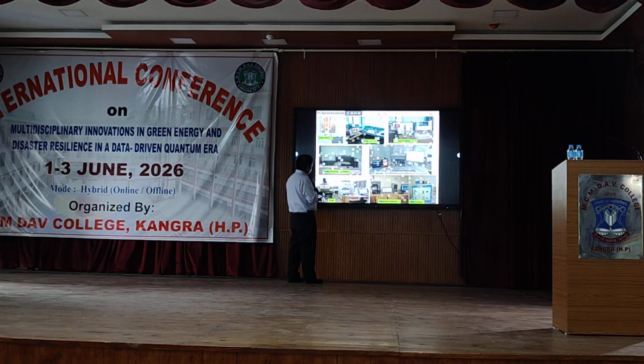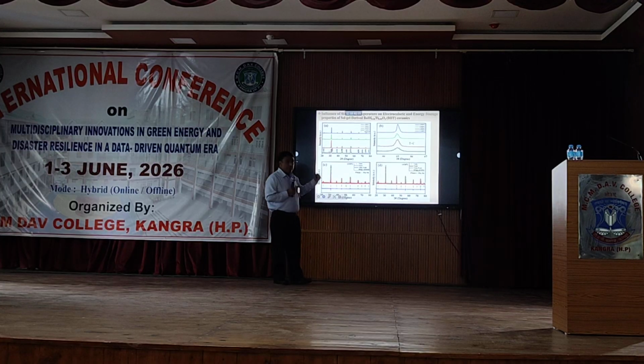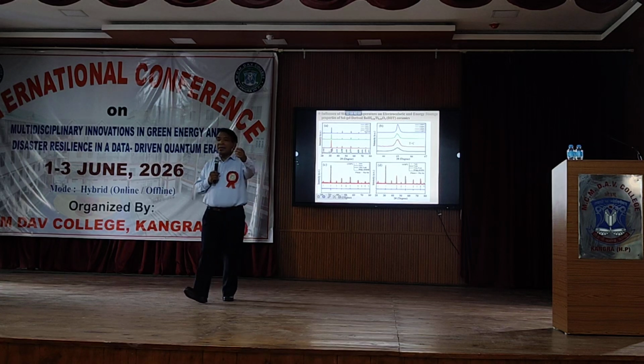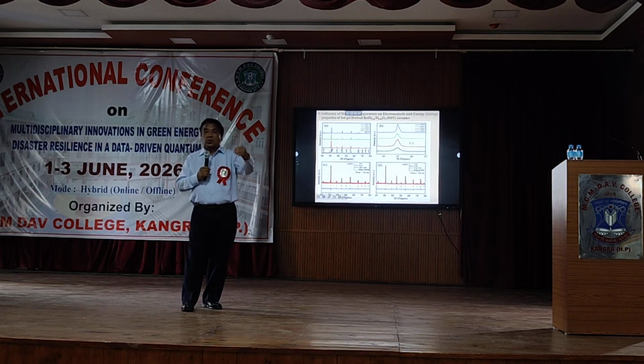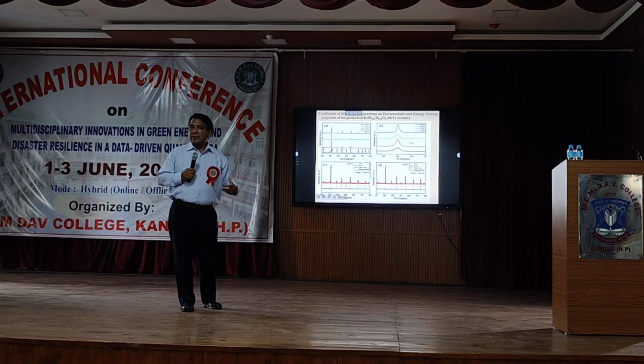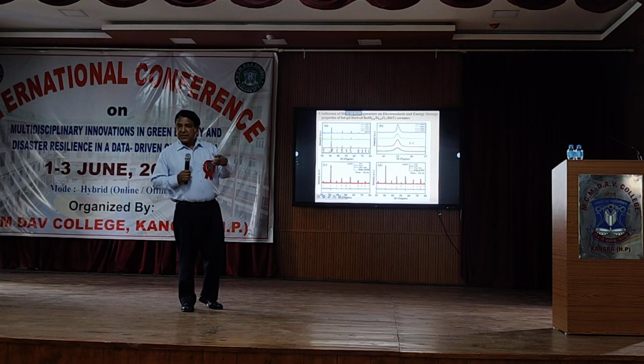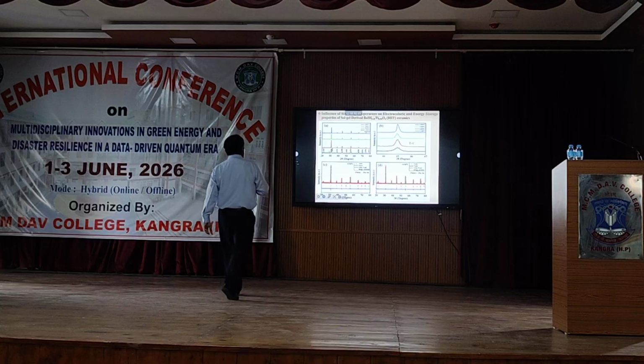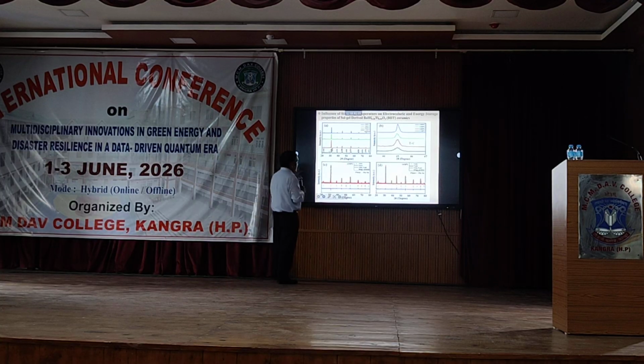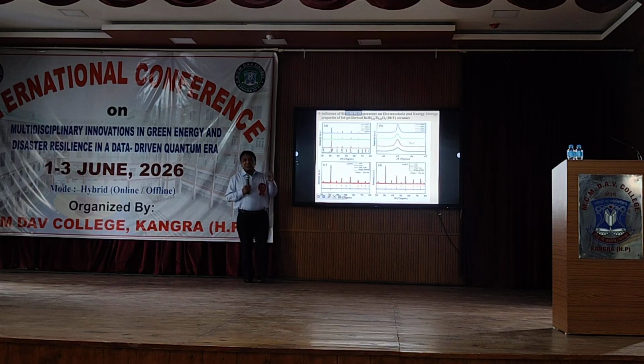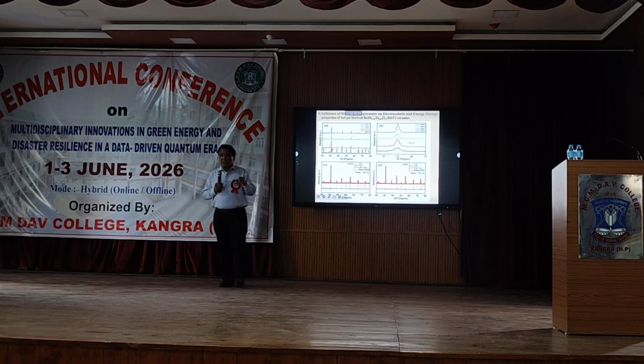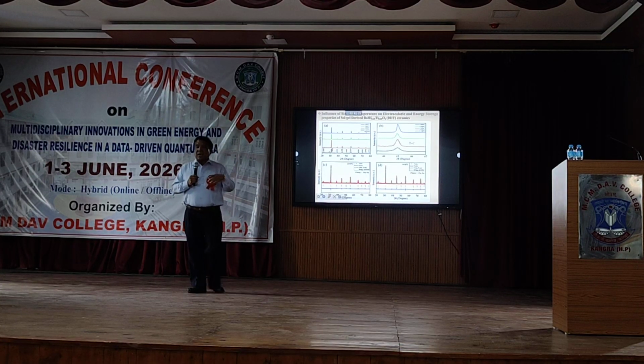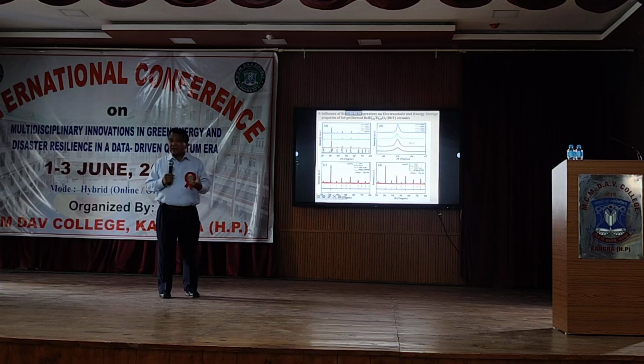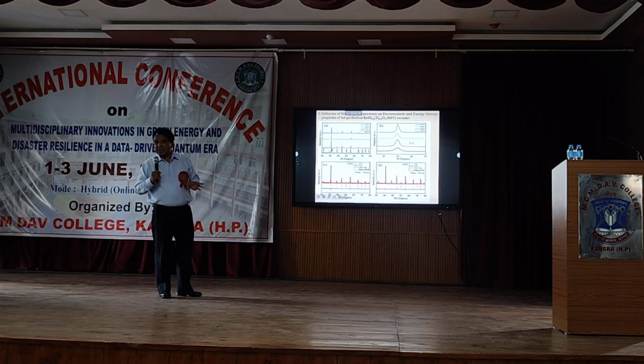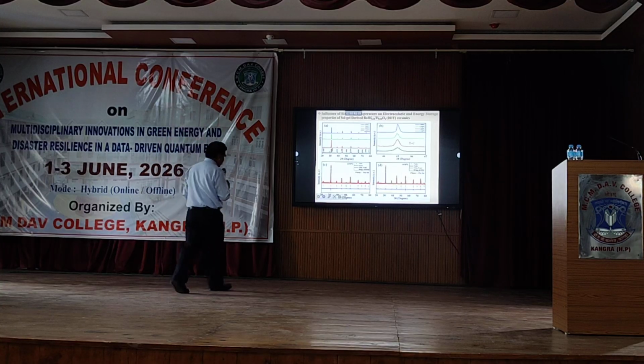Anyway, we selected this hafnium-substituted barium titanate because hafnium substitution can bring the Curie temperature from 130 degrees close to room temperature, so as to have a significant change in temperature, the electrocaloric effect, near room temperature. The sintering temperature is again crucial because sintering temperature affects the microstructure, and microstructure affects the relaxor ferroelectric formation, and finally the prime properties, that is the electrocaloric effect and the energy storage property.